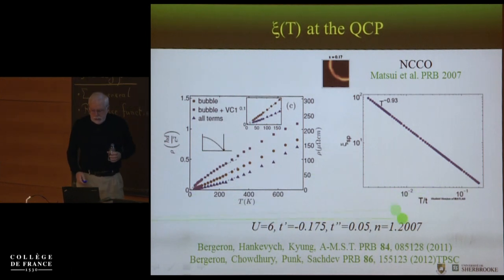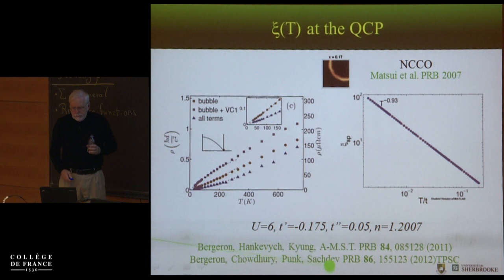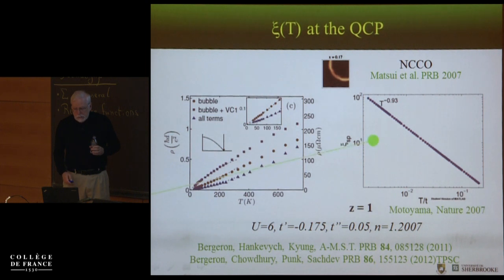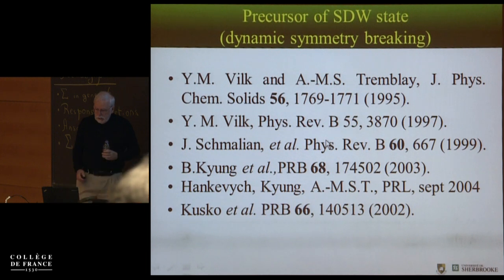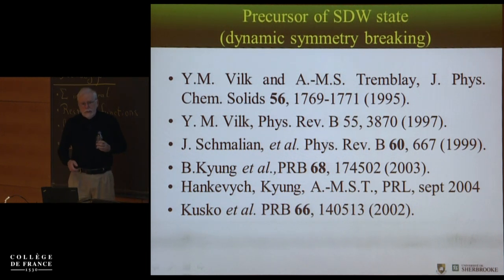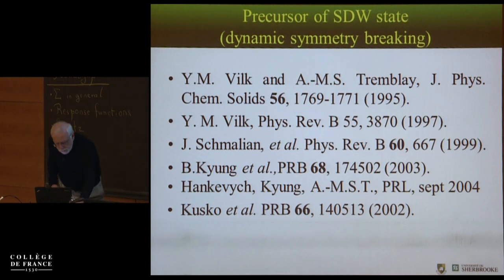That's just another calculation that we did with Subir. In this experiment, they showed that Z, the dynamical exponent, was equal to 1. And if you do the calculation in the regime that seems to be the case experimentally, you find this exponent 1. I could come back on this, but the point is that everything seems to be consistent. Since the PDF will be on the network, you can look at the references.